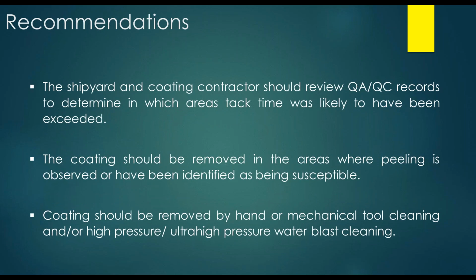At the conclusion of the investigation, our recommendation to our client was for the shipyard and the coating contractor to review QA and QC records to determine in which areas the tack time was likely to have been exceeded. Furthermore, it was recommended that the coating should be removed in those areas where the peeling was observed or had been identified as being susceptible. It was recommended that the coating be removed either by hand or mechanical tool cleaning and or high pressure or ultra high pressure water blast cleaning.